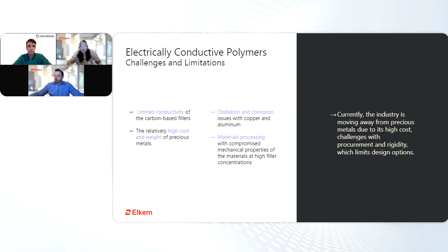So using fillers that we have commonly heard of today, there are still many challenges that pose to today's industry that have not made conductive plastic as common as we would like to see them in today's market. One, there's still a lot of limitations to conductivity that can be achieved using carbon-based fillers. Two, it's still relatively expensive in terms of cost and weight when engineers use traditional precious metals. And with using some metals, there's a risk of oxidation and corrosion issues, especially in aluminum or copper. Loadings of fillers at higher concentrations can limit your mechanical properties, like how it can make your material become more brittle if you use too much, etc.